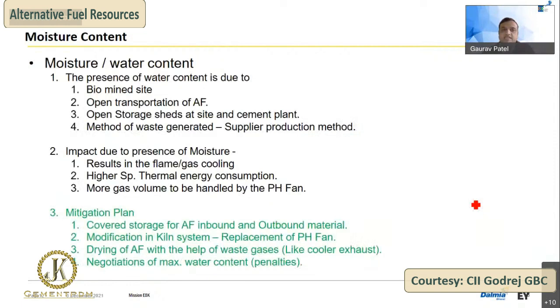Next, if we see moisture, this comes from biomining sites, since most of the RDF comes from biomining. There is open transportation of AF, and there is a lack of storage sheds at the site and the cement plant. The method of waste generation also depends on the supplier. This results in flue gas cooling and higher specific thermal energy consumption because of higher moisture content, 40-45% also. Indirectly we have to handle more gas volume with the same preheater fan while maintaining the clinker TPD. So our mitigation plan is covered storage for AF inbound as well as outbound material, and whatever shed we have, that also has to be covered.